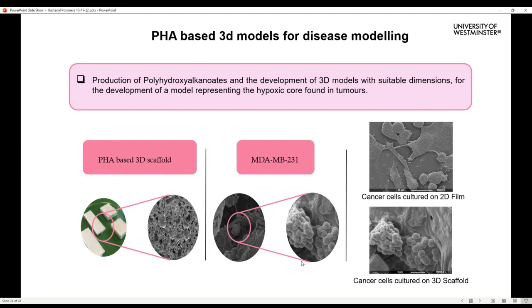Here, instead of culturing a tissue outside of the human body, we're trying to create a tumor outside of the human body. Instead of growing healthy cells, we were trying to grow cancerous cells, using these bacterial polymers again as a scaffold. So far we've looked at 3D printed structures, fibrous structures, and tubular structures. In this case, we created these 3D structures by simply making a polymer solution and pouring it into a Teflon mold. It was almost like the process of baking. You take the mix, you put it on this mold, you allow it to dry for a few days, you take it out, and then there you have your three-dimensional structure.